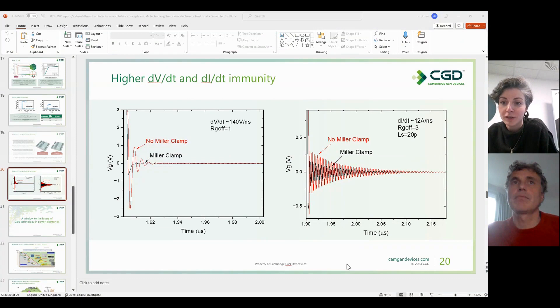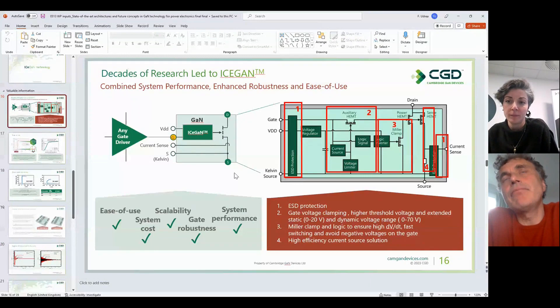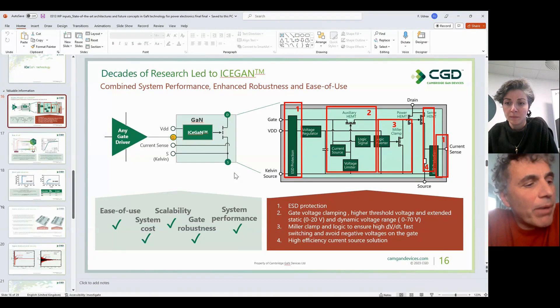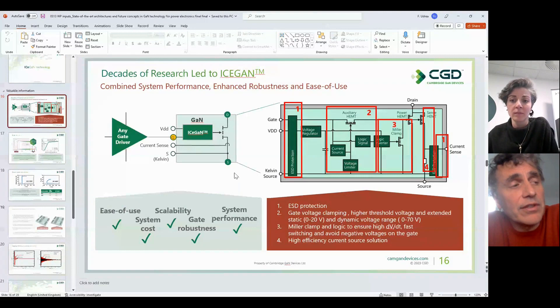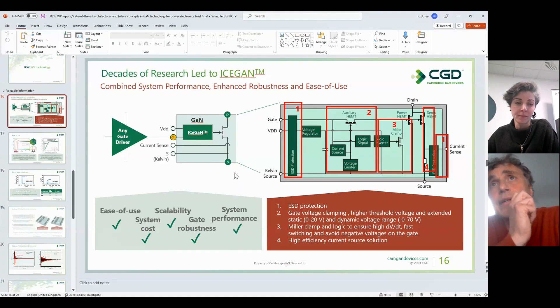Kengo Omori asks: how did you achieve higher threshold voltage — from GaN device structure optimization or an external circuit? The answer: increasing threshold voltage from the device structure itself is extremely difficult because it can compromise channel resistance. Instead, we introduced an auxiliary HEMT that adds voltage to the gate so that the requirement from the external gate is that both the auxiliary HEMT and the power HEMT must be on simultaneously, effectively raising the threshold voltage.